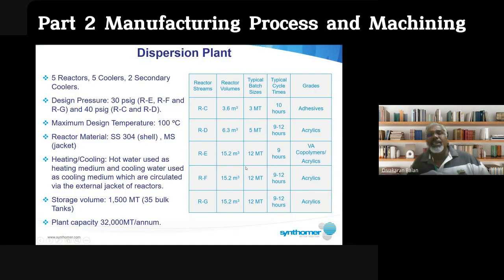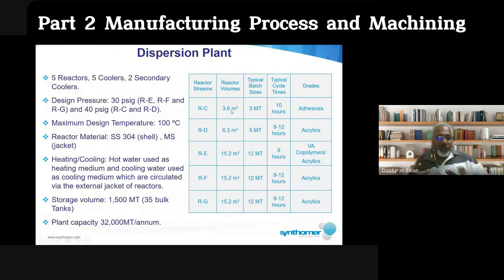Here, reactor C. If you see the volume on the right side of the screen, reactor C volume is 3.6 cubic meters. So it's not big, it's a small reactor, about 3,600 kg each time you process a batch. The typical batch is 3 metric tons. Normally the batch we produce is lesser than the reactor volume, otherwise it will overflow. So the formulation recipe given for each product is lesser than the reactor volume.